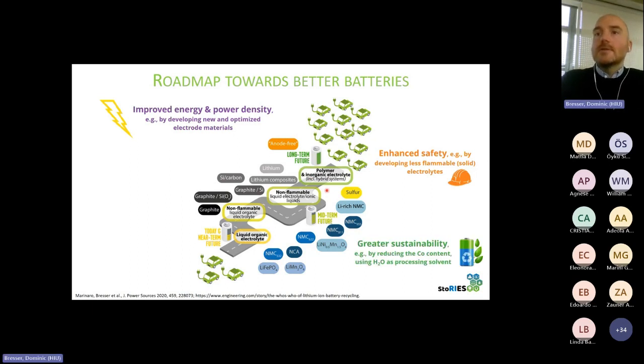And when talking about greater sustainability, as I said, this is largely about the positive electrodes. So we have here LFP, which is quite sustainable already, but would benefit from some boost in energy density. And then we have NMC, the different kinds here. So that means it's about an increasing nickel fraction, especially a decreasing cobalt fraction. And then eventually the target is to have manganese-rich cathode materials, since manganese is much more abundant than nickel even, and less costly.